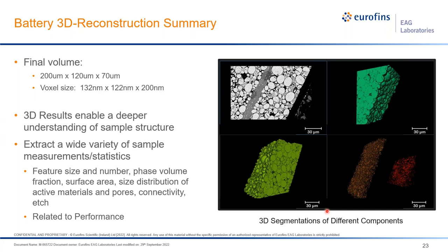to be able to provide you more information and a deeper understanding about your complex structures, especially electrode structures like this. So information we can then obtain from this kind of segmentation are things like phase volume fraction, surface area of particles, size distribution of the active materials. And we can also get deeper understandings of things like porosity and particle connectivity that can actually be quantifiable, so we can then track this from sample to sample.